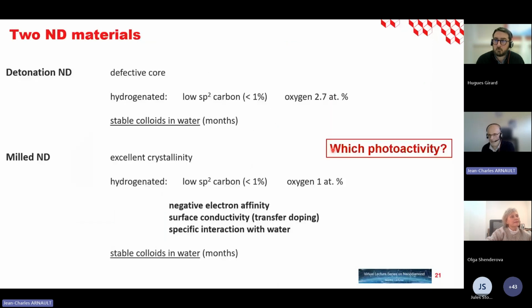To conclude, and then to give the floor to Hugues, we have two main nanodiamond materials. The detonation one has a defective core. As it is hydrogenated, we lower the sp2 carbon and the oxygen at the surface, and we get a stable colloid for months. It is important for photocatalysis experiments. For MND, you have this excellent crystallinity of the core. As it is hydrogenated, you also have low sp2 and low oxygen, and you have additional properties: the negative electron affinity, the surface conductivity, and specific interaction with water. And we also have a stable colloid in water. The question now is, which photoactivity? So I will switch and give the floor to Hugues.